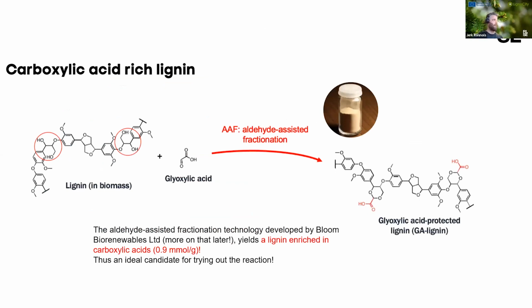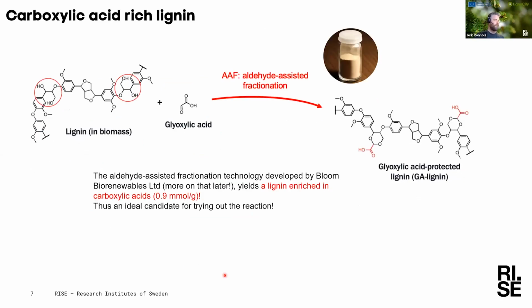So to start out, a carboxylic acid-rich lignin, well, we were lucky enough to be in contact with the Bloom Biorenewables, who specialize, well, what they specialize in, Justine will be able to tell us later on, but in their process, they can make a very carboxylic acid-rich lignin through their aldehyde-assisted fractionation, as they call it. So they go from lignin here with glyoxylic acid, which forms acetals over the beta-O4 bonds, and introduce carboxylic acid groups here. So the resulting lignin has 0.9 millimole of carboxylic acid groups per gram, which is quite a lot compared to lignin, which is usually around 0.1 plus minus a few other decimals there. So this seemed like a very good candidate for trying out the reaction.